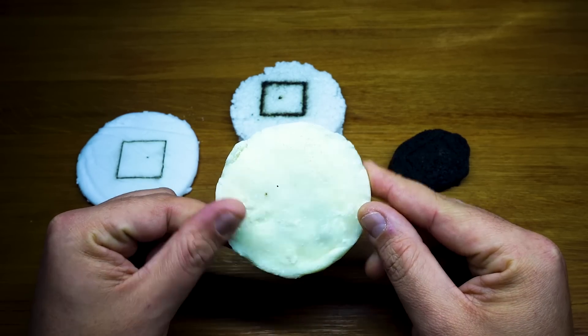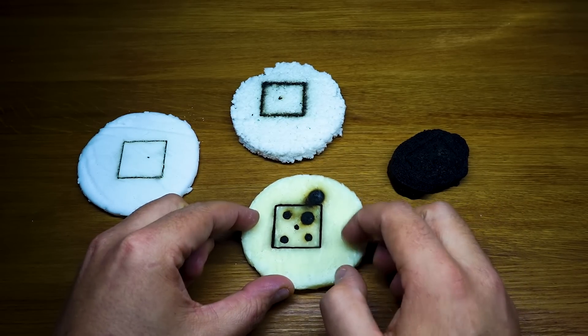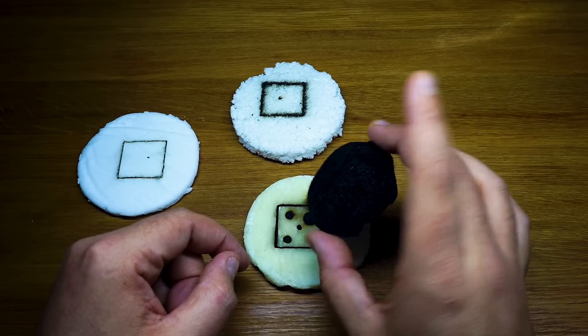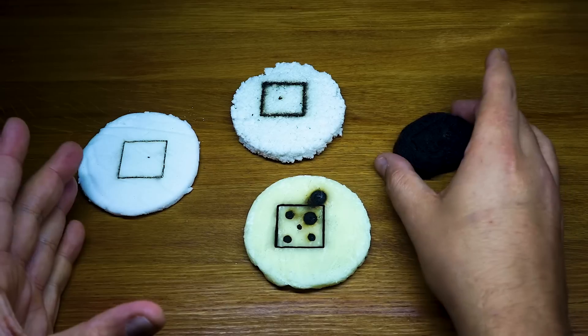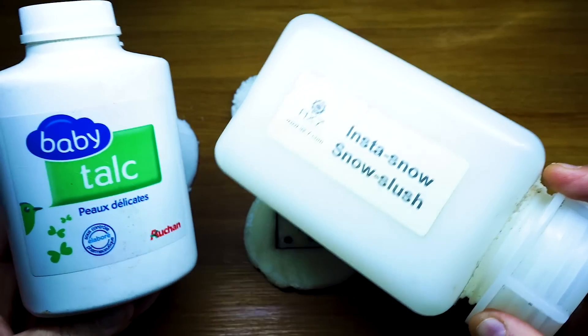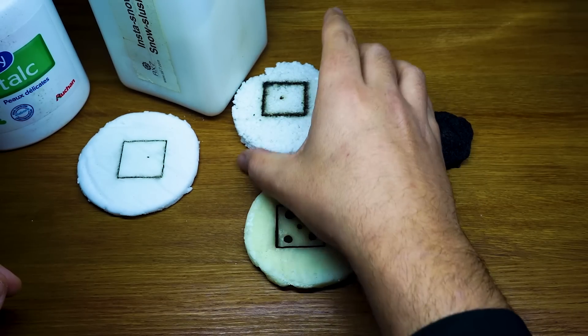As a conclusion: if you want to experiment with homemade Starlite, the recipe with cornstarch and baking soda is the way to go. It is the cornstarch that gets carbonized and builds up a pretty heat-resistant layer. The carbonized bread also made a pretty good heat shield, though it will disintegrate over time when exposed to very high temperatures. For those who want to know what I put in my own concoction: it was SAP — a super absorbent polymer used to make snow slush for movies, sometimes found as 'insta snow' in stores. I mixed it with talcum powder and baking soda, but my theory of making a foam-like polymer disc went totally wrong and it failed after only two rounds.